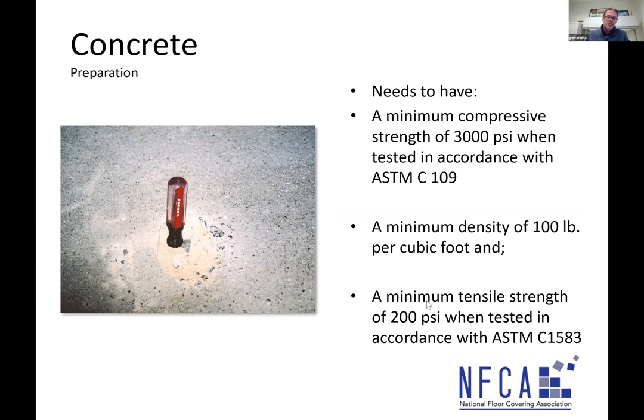Another industry standard is tensile strength, which is basically pulling something apart until you get a failure. It's very common that the tensile strength is roughly 10%, maybe 15% of the compressive strength, just from a mathematical standpoint. But from an industry standard, the concrete should have at least 200 pounds tensile strength, and that test is conducted in accordance with ASTM C1583. So three good things to keep in mind: the concrete compressive strength, at least 3,000; tensile of at least 200; and if it's lightweight concrete, it's got to be structural, at least 100 pounds per cubic foot.